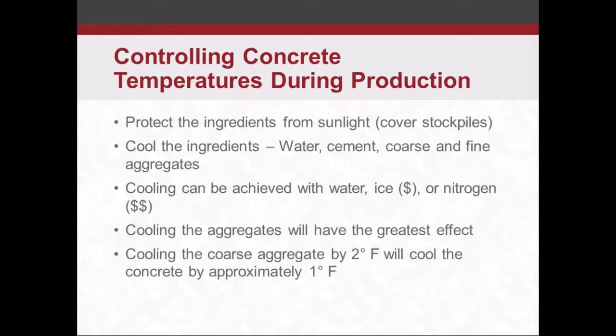Down south, they use nitrogen. They'll take a lance and put that lance into the discharge of the concrete truck, and they'll spray some nitrogen gas in there, and they'll cool it down that way. We don't see that too much in our area up here in the Northeast because that's pretty expensive. But again, cooling the aggregates, that's going to have the greatest effect. It's probably going to be the most economical. Cooling your aggregates by about 2 degrees is going to drop your overall concrete temperature by about 1 degree. So cooling those aggregates is definitely going to have the greatest effect.